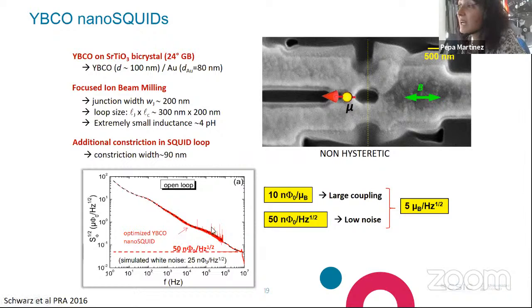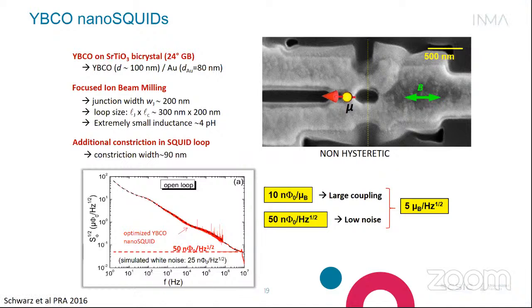Yeah, well, this is typically ascribed to vortices in the high TC, and especially flips in the superconducting current through the junctions in the SQUID. We also ascribe these high levels of flux noise to the presence of spin noise in the device itself, very probably coming from the STO, although this is also observed in substrates grown in other oxides, but the spin noise is probably playing an important role. Yeah, it would be really nice to be able to decrease this contribution. Right. I think it's the same thing. You're right. Even in the conventional SQUID, the 1/f noise is mostly blamed on spin noise at the interface, I think.